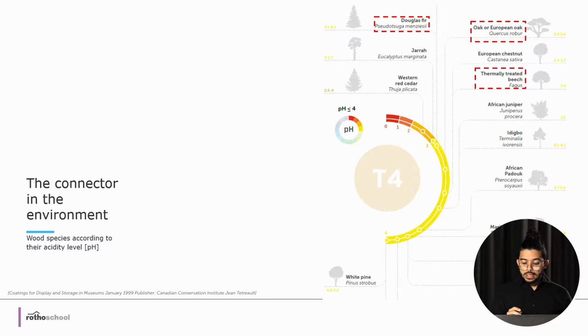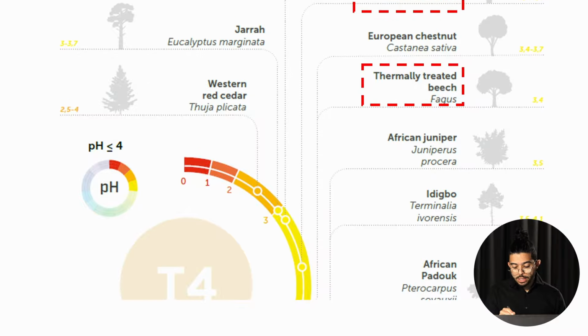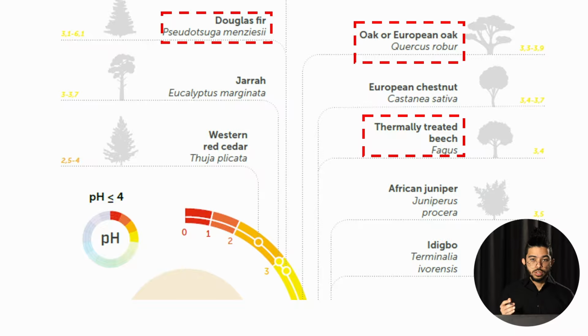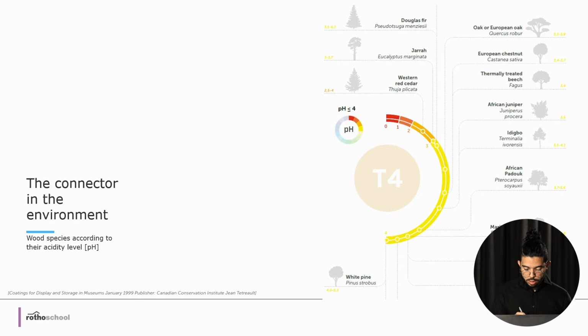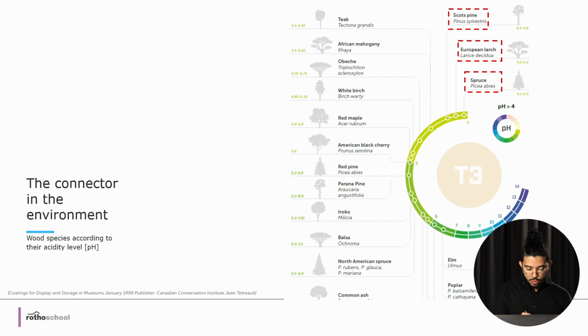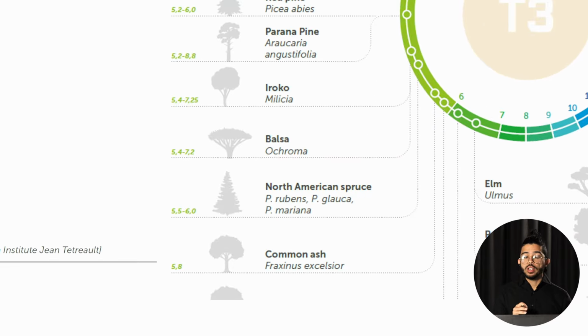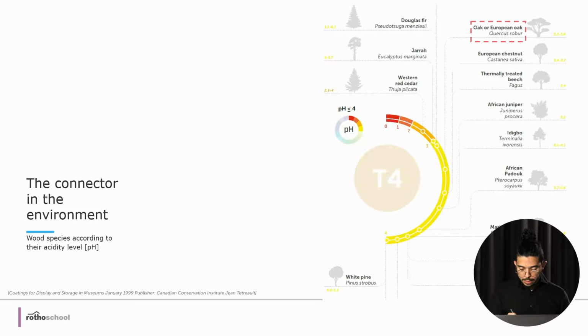And a very interesting case is the case of thermally treated woods. So you can see here, let me just zoom here, that thermally treated beech has a 3.4 pH, which is very acid. The limit is 4. But untreated beech, which you can find here, has a 5.9. So the thermal treatment has a strong influence on the pH, and changes even the pH and the aggressiveness of the element. So be aware that thermal treatments can also affect the acidity and the aggressiveness of these elements, of the trees and the timber.